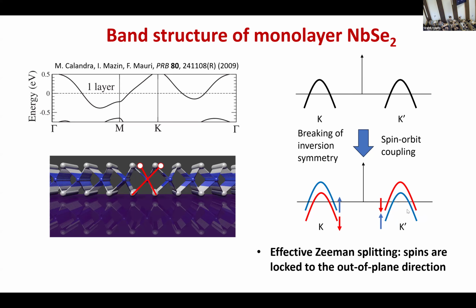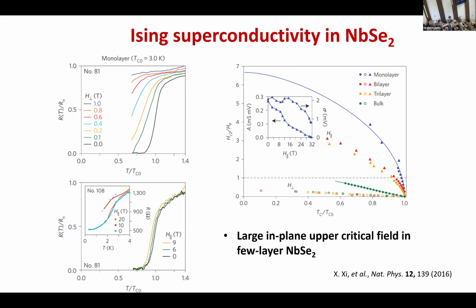So due to this so-called spin orbit coupling induced spin splitting, we have the spins somehow losing degrees of freedom. So they are locked just along the z-axis. This is why we call this Ising pairing, because the spins have only one degree of freedom. So with this, how do we understand this largely enhanced upper critical field? People observe that the upper critical field could exceed the Pauli limit that we explained previously, which is just 1 in the reduced plotting, and it can exceed this Pauli limit by a factor of, from the experimentally available magnetic field, about 4, but if you extend that, it can be even 6 or 7.